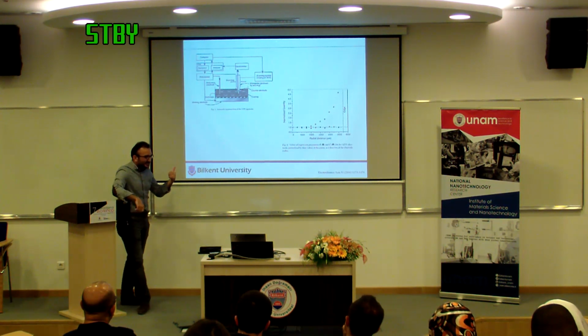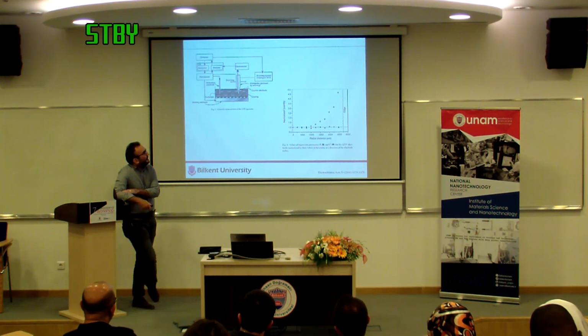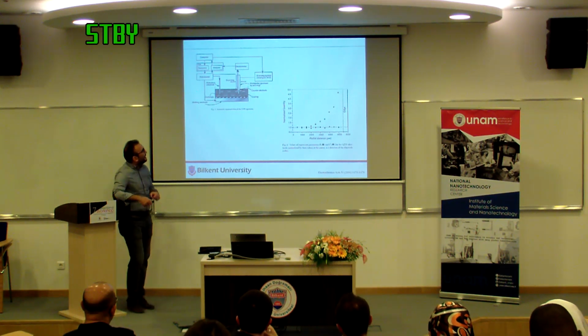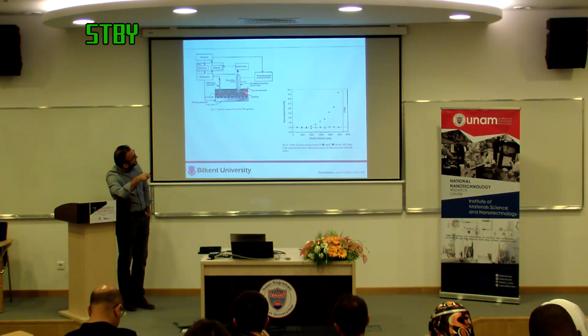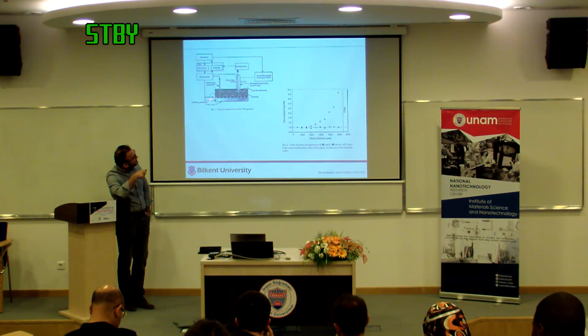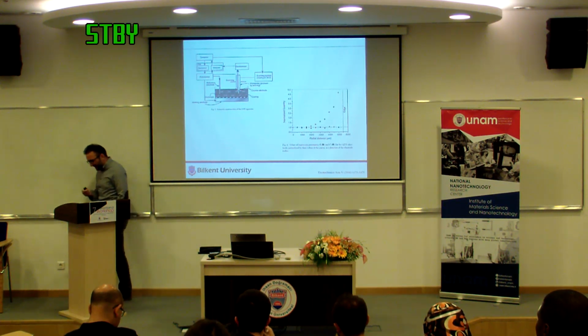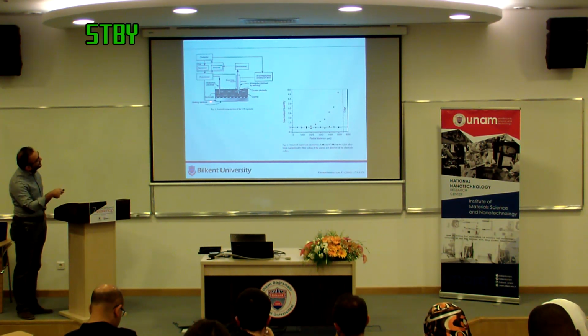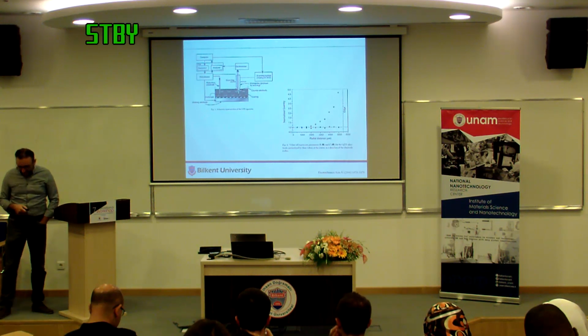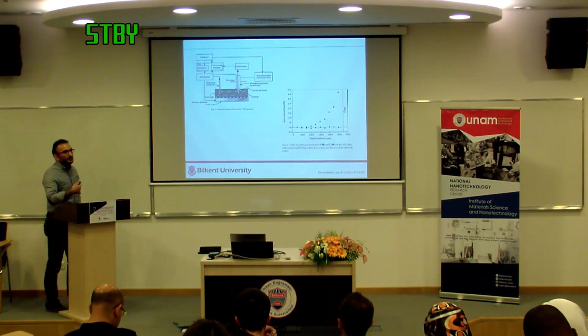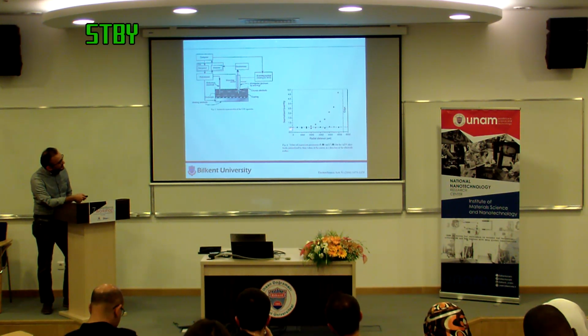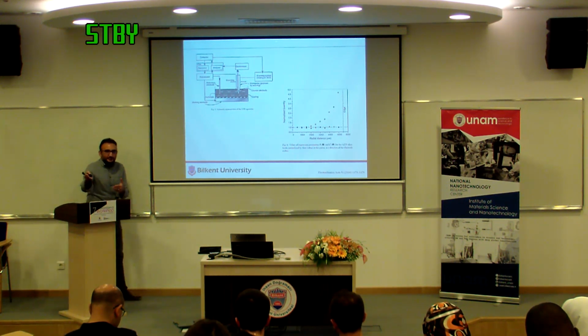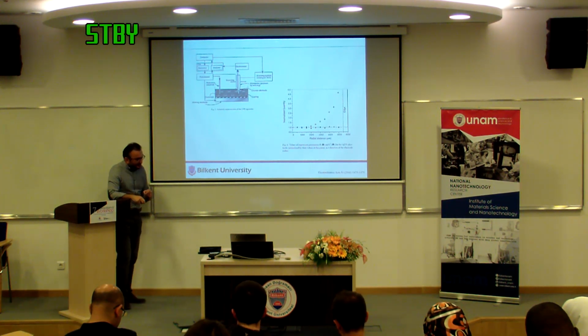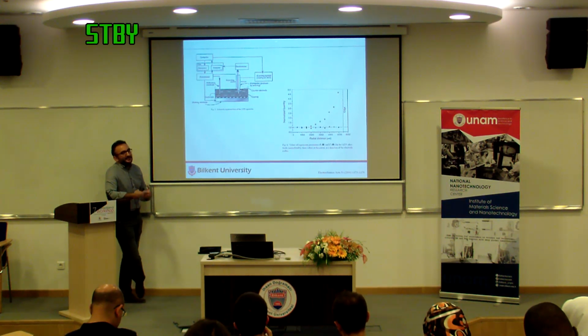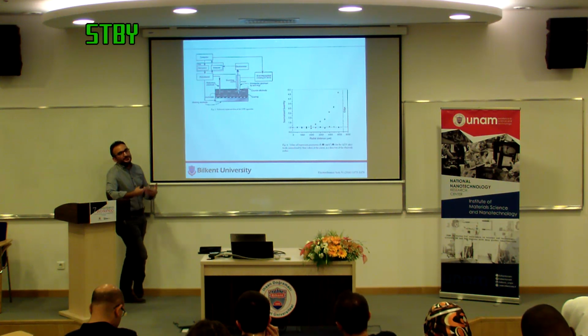In one of them, this is from the group of Vincent Vivier in Paris. What they do is they do localized EIS measurements. They have a surface and they come with a probe and they scan this probe, measuring the impedance across this interface along the sample. Now the point is that they have a reference electrode here and a counter electrode somewhere. And as they move their probe close to or far away from the counter electrode, they are seeing that the capacitance is constant, but the resistance changes. And the resistance changes just simply from the distance. And what they're saying is that it's this distribution of the resistances that's leading to a distribution of time constants that's leading to a constant phase element behavior.